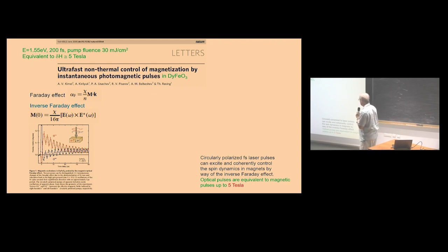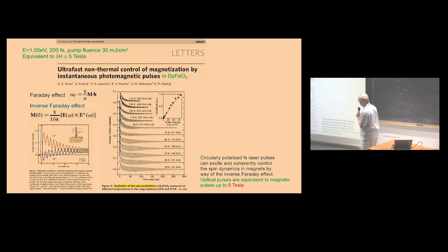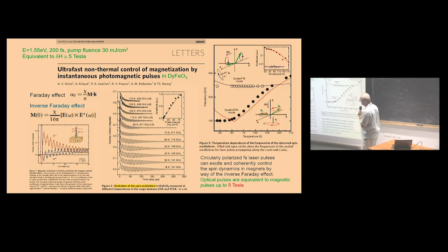In this case they used, again, femtosecond lasers, and for these oscillations, if you calculate the Fourier transform, you finally obtain the spectrum. It means that they obtained the quasi-antiferromagnetic resonance and the quasi-ferromagnetic resonance in this dysprosium ferrite. What does it mean here?